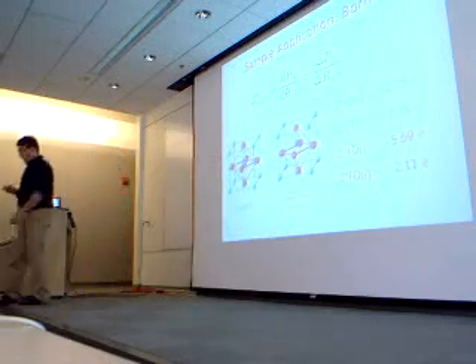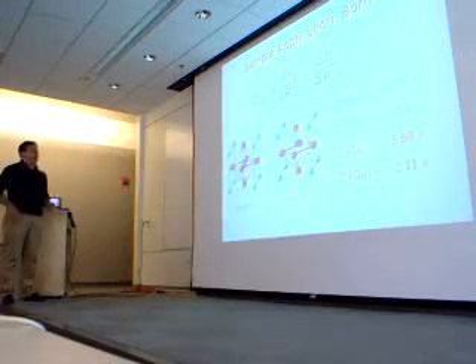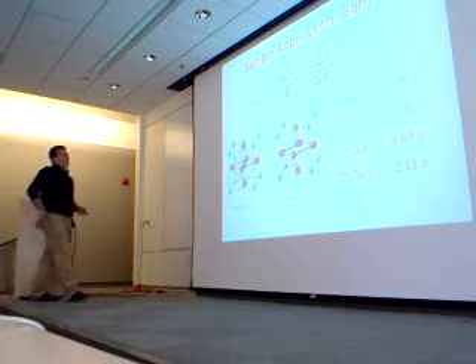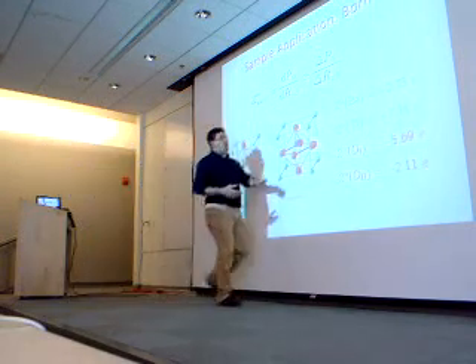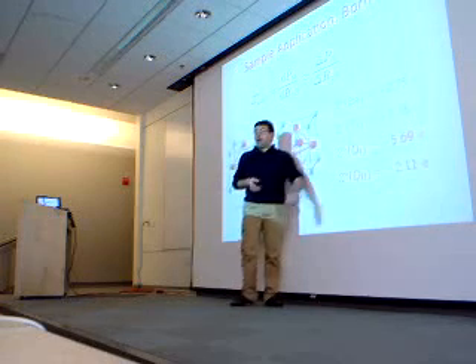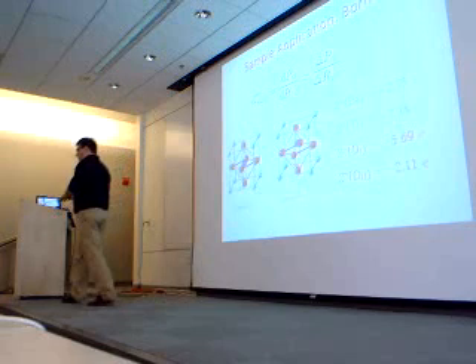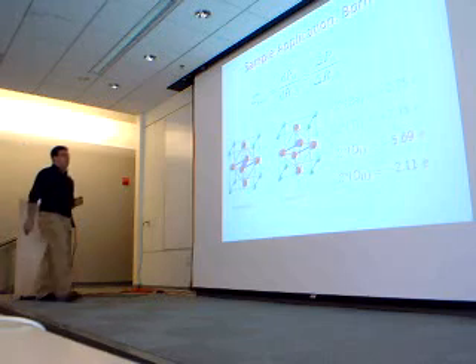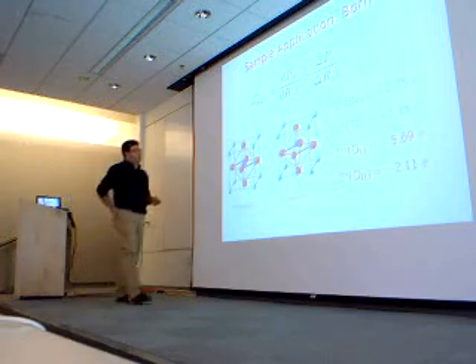And actually, these can be measured not exactly in themselves, but the effective charges really give the splitting between the transverse optical and the longitudinal optical phonons in the phonon spectrum at gamma of a material. And so you can calculate this, and from this and the dielectric constant of the material, you can actually predict what that splitting is. And that splitting is huge exactly because these are large. And the issue is that the longitudinal optical modes are infrared active and the transverse are not. And so the coupling with the electric field is very different in the two cases.